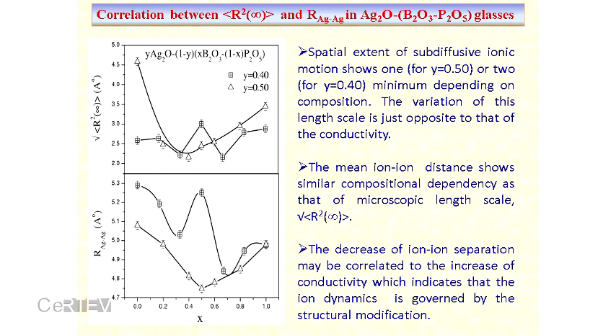It is a dynamic parameter. So it depends on some dynamic parameters, that is the crossover length, or the length at the crossover time or crossover point. Here I have shown the long time behavior of this parameter, at time t equal to infinity. Particularly this corresponds to DC conductivity. You can see the opposite behavior. For 0.5 there is one minimum, and for 0.4 there are two minima. And this corresponds to similar behavior to the activation energy. Or if you calculate the average silver-silver distance here, you can see the behavior of the silver-silver distance is the same. So we can at least predict that this parameter is very close to the average mobile ion distance in the glass system.